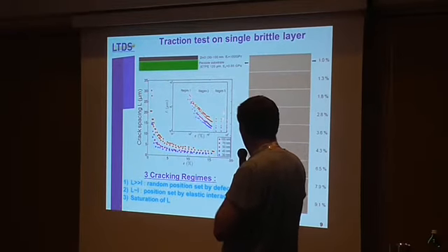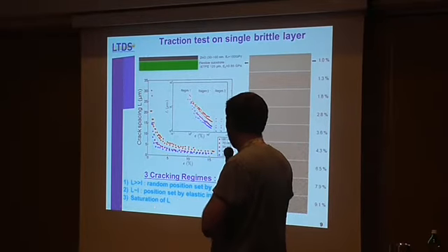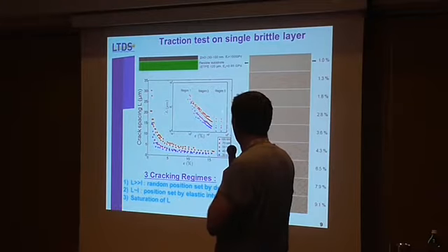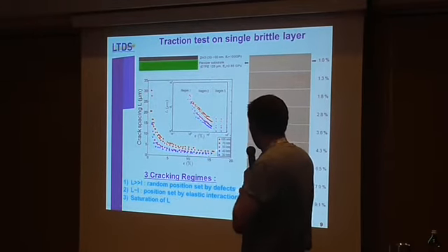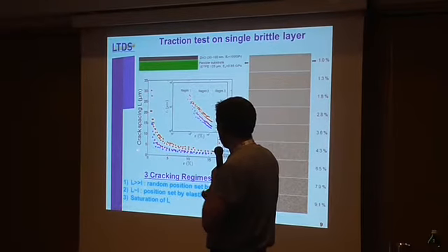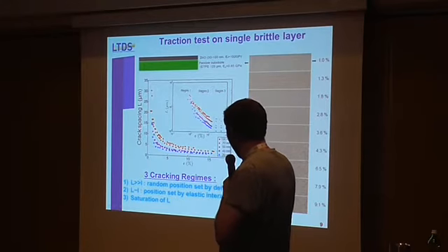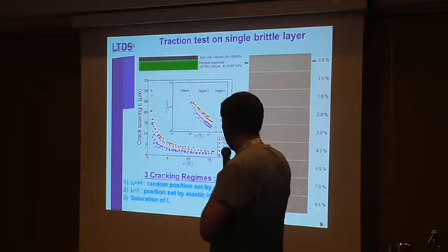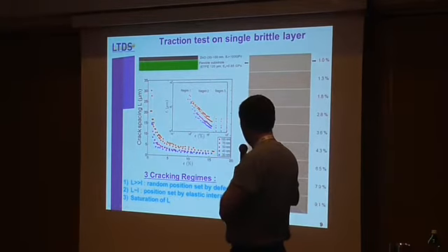What is interesting is that at high enough strain we observe a saturation of this crack length, which depends on the thickness of the film and is of the order of some micrometers, whereas the thickness of the zinc oxide is of the order of 100 nanometers.